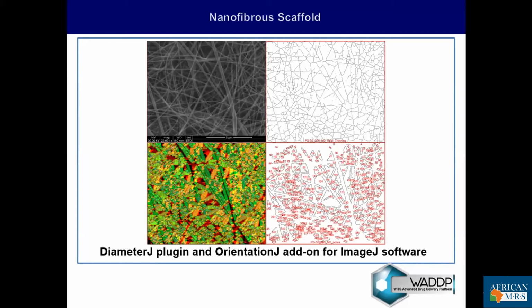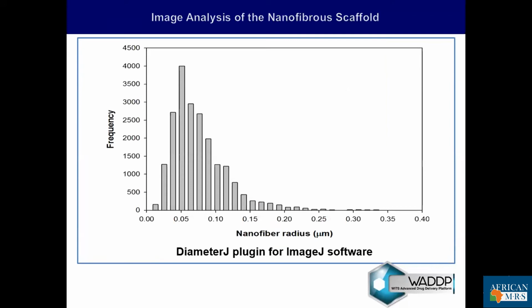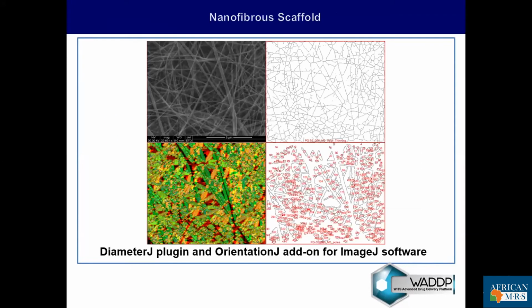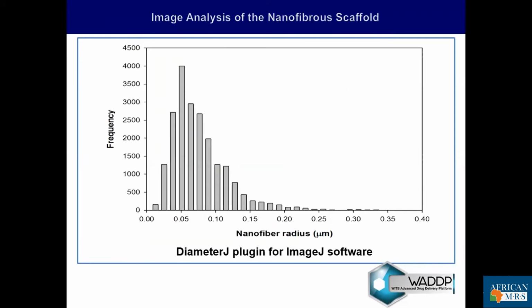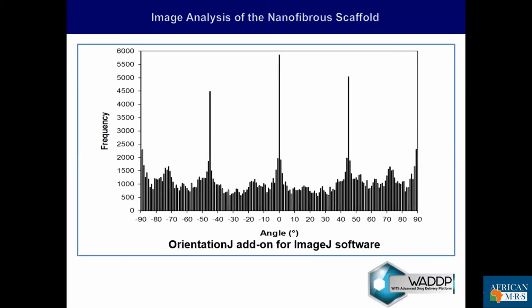We do a lot of image processing of nanofibers. You can see in the front, we have nanofibers, and then we do a porosity analysis using ImageJ software. Then you can check the size of the nanofibers using the DiameterJ plugin. For example, in the previous one that I'm showing here, you can see most of the nanofibers are in the size range of 50 nanometers, but a few of them can go up to 300 nanometers. But mostly it is in the range of less than 100 nanometers, and we can call them nanofibers. Again, orientation is very important, so we use OrientationJ for checking the orientation. You can see from 0 to -90 and 0 to 90, they are mirror images.